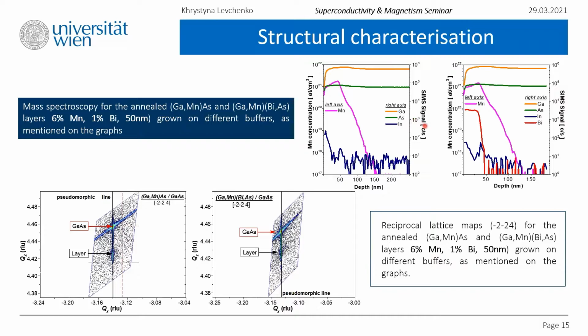In the images you may see in the top right corner, the left-hand axis is the manganese atom concentration per volume unit, per centimeter cubed. And the right axis is the concentration of other components, while here is the penetration depth of the corresponding signal. So what does it mean? That we expect gallium, manganese, and arsenic in the case of the ternary compound, and gallium, manganese, and bismuth arsenide in the case of the quaternary compound. Below it is a buffer, again, gallium and arsenic only. So after 50 nanometers, we should see only signals from gallium and arsenic in both cases. And it is the case in our samples.